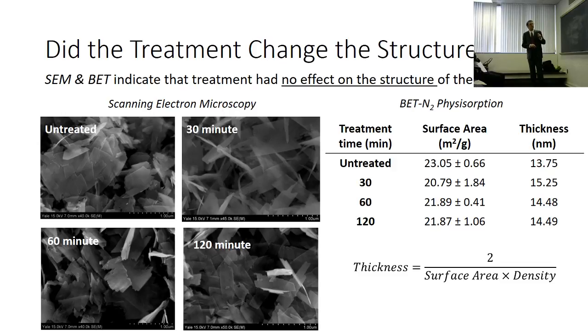So instead, another technique to measure structural changes: I did BET, which is a surface area measurement. Maybe there was a little bit of surface area change, but not any trend, not really anything to write home about—it's very small, if anything. So I concluded that the treatment was having no effect on the structure.